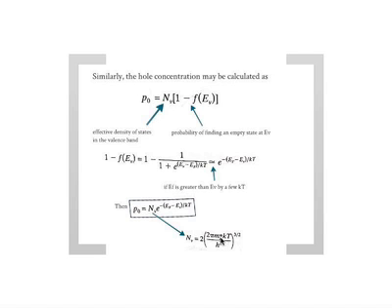So you can see that NC and NV have the same equation, except that the effective mass is one for electrons, one for holes, and they can be different, right? Because the band curvature is different. For gallium arsenide, it's roughly the same, but for silicon they're different, which means that you can have different concentrations of available states for holes than you have for electrons.